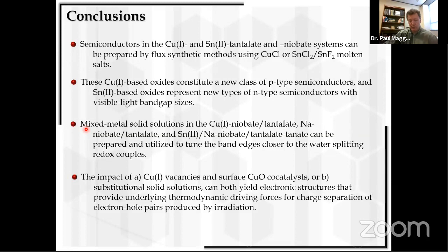And not only that, and I haven't had time to discuss this, but you can make metastable phases using solid solutions. In other words, kinetically unstable phases can be stabilized using solid solutions because you have the multiple cations kinetically trapped onto their sites. So you can exchange in higher amounts of tin or higher amounts of copper, even beyond thermodynamic stability. And in the case of copper 1, how important the surfaces are, especially putting copper oxide onto the surfaces.